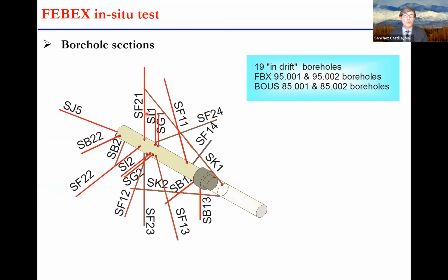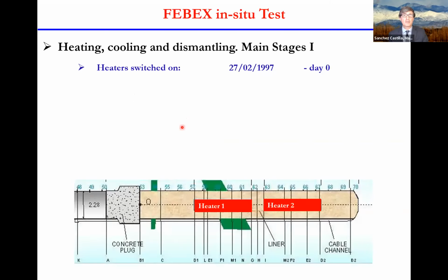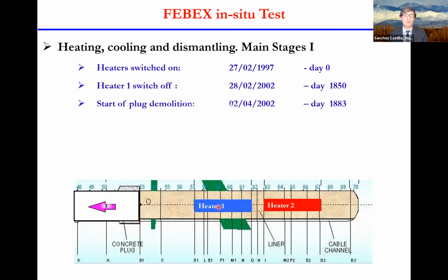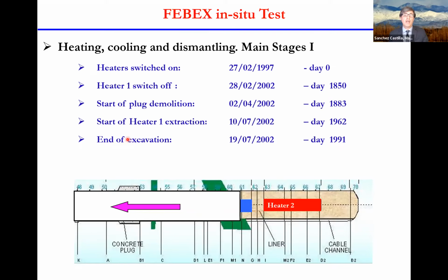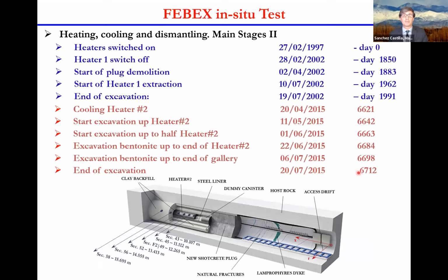We also have boreholes around the gallery. So this is the gallery, and the concrete plug. And these are boreholes around this gallery to understand the thermal, mechanical, and hydraulic field around it. The experiment ran for around 18 years, with two main stages, starting in 1997. After 5 years of heating and hydration, they decided to switch off heater one, and we dismantled the first part of the experiment. Then the experiment continued for another 13 years, until 2015, when it finished.